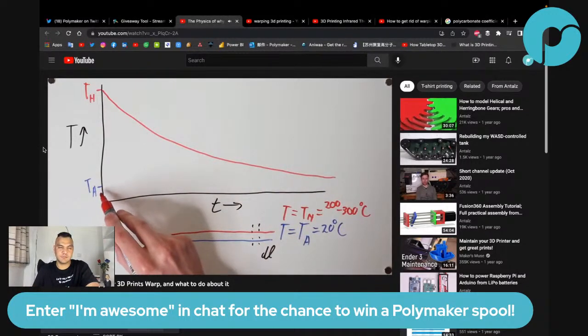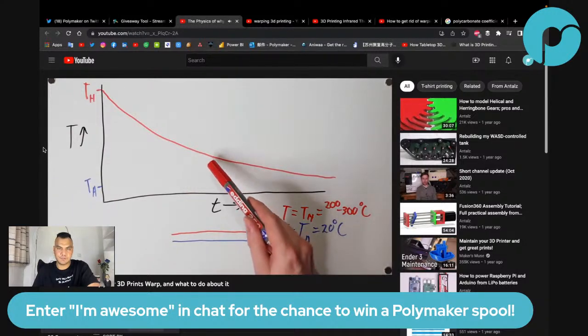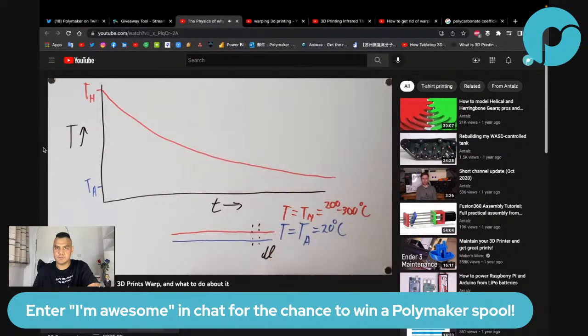Until it reaches around the ambient temperature. And this is because of two effects. First, it will lose heat into the atmosphere surrounding the print. And second, it will start losing heat to the colder lower layers below it. So his explanation of why it's exponential decay is that it loses heat to the atmosphere and to the layer below it. But I don't think that explains why it's exponential. It explains why it decreases, but it doesn't explain why it's exponential.